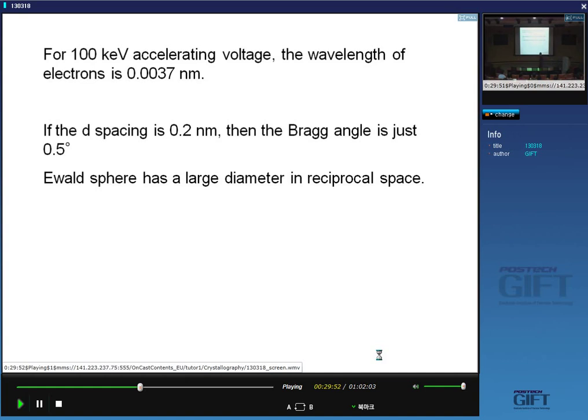In your electron microscope, the Bragg angles will be much smaller than when you do X-ray diffraction, because the typical wavelength of an X-ray is about 0.15 of a nanometer. So in a transmission electron microscope, when you see an incident beam and a diffracted beam, the angle between the diffracted beam and the incident beam is, you know, almost zero. Okay, so that's quite important to remember.